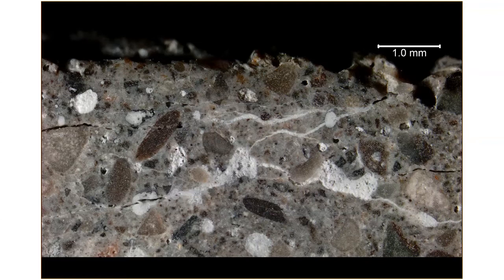And we still have, in most areas of this pavement, an original surface that's seen quite a bit of mortar erosion and traffic wear, but the aggregates are staying there. But we don't see this scaling or spalling of a typical exterior flat work undergoing freezing and thawing and surface distress. This has self-healed. So very interesting petrographic anomaly here. But again, showing you a number of things that we're seeing that were very special about this pavement.